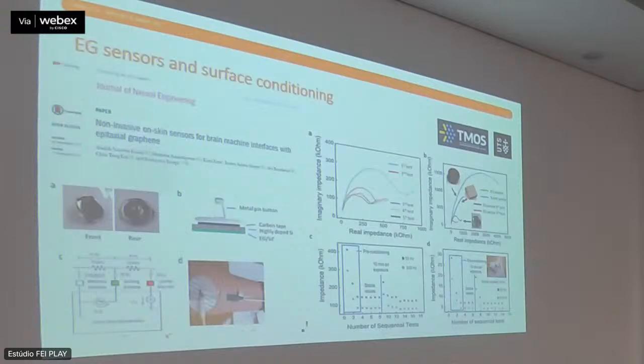So there is actually a very high need for extremely good dry sensors, and that's where the graphene comes in. Now, it turns out that graphene is biocompatible. Graphene can be intercalated, as you remember, and there's some interesting stuff happening here. So what we decided to do is to look into the potential of this system as a sensor. And what we're doing is actually very simple. We're just using this graphene on silicon carbide, so it's very, very thin, and connecting that to the backside of the silicon into the socket of the helmet through a pin button.